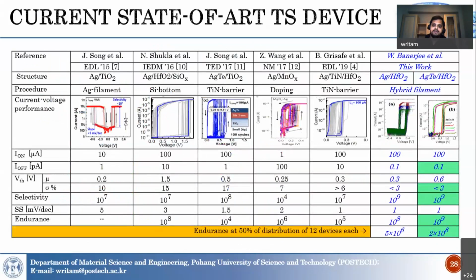So here is the summary of these threshold switching devices, and you can see different groups' work is presented here. Normally with this scheme, using hybrid filament formation, we can minimize the variation of the threshold voltage to less than 3%, with very high selectivity of 10 to the power 9, and very high endurance of 10 to the power 8.